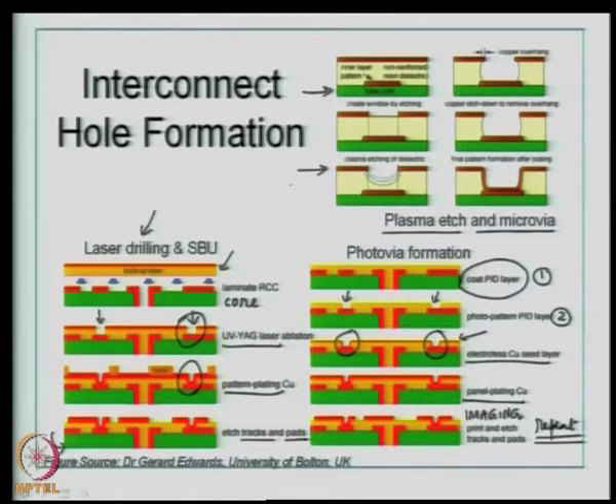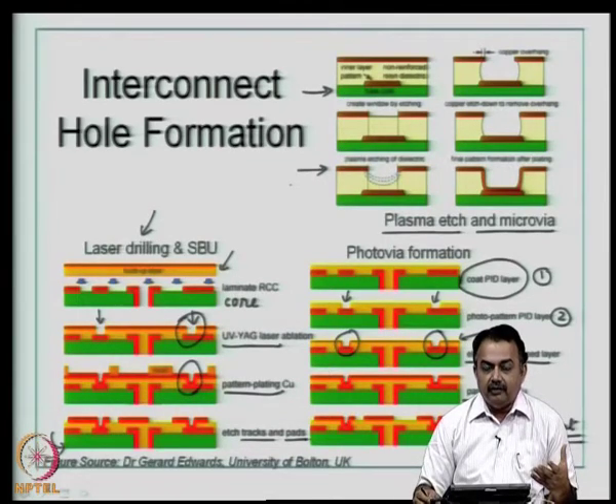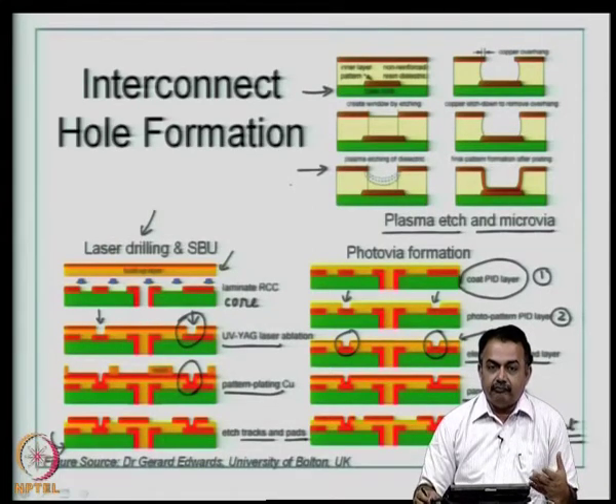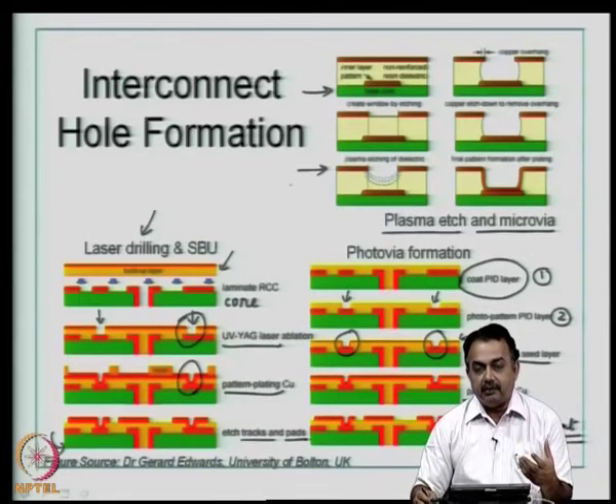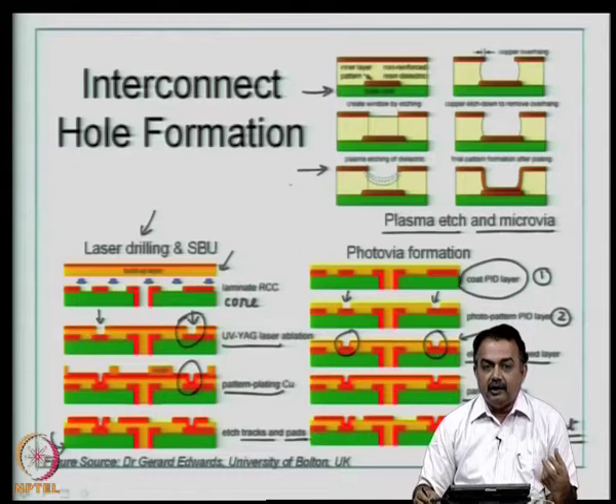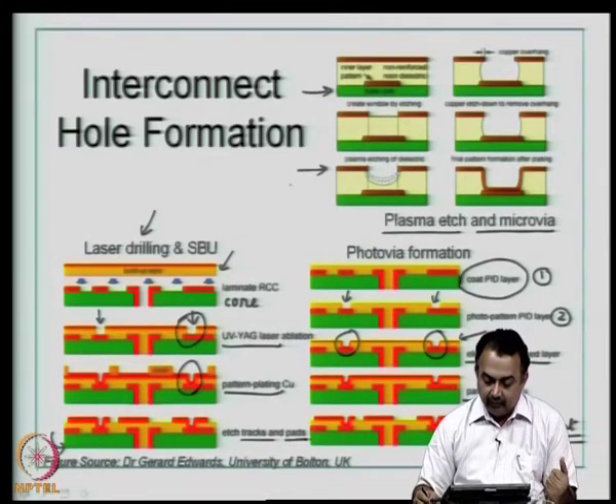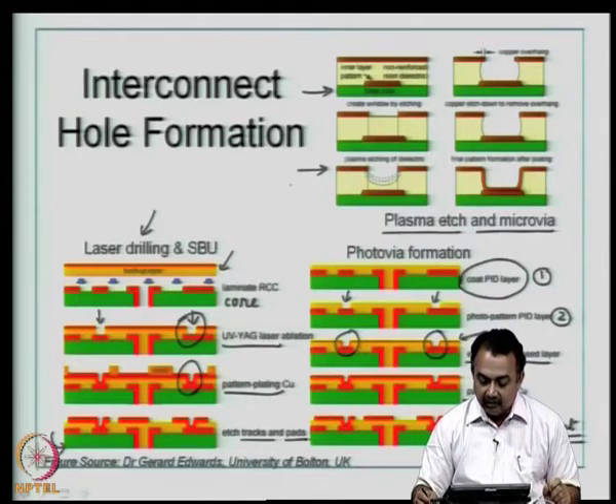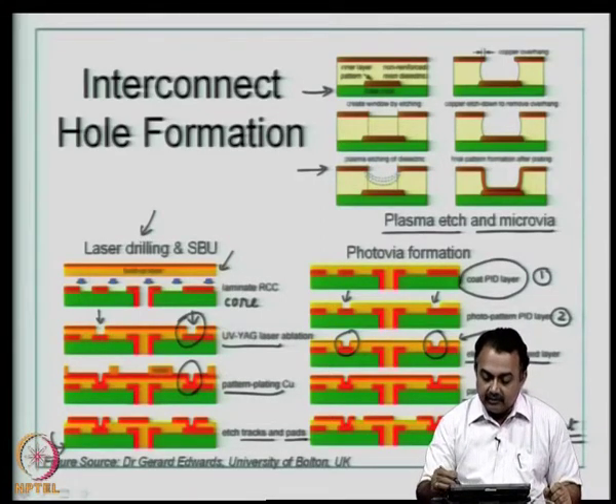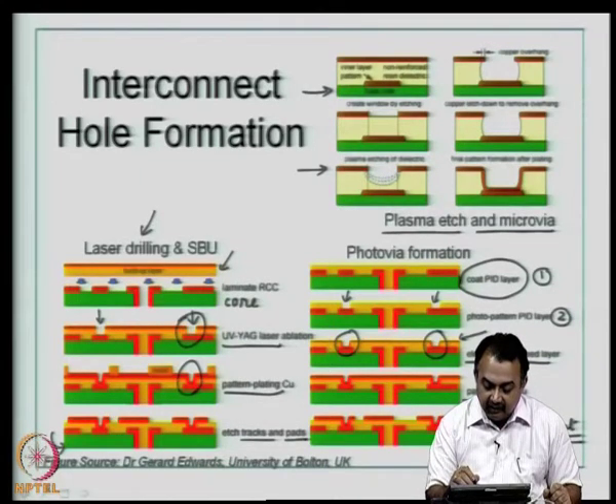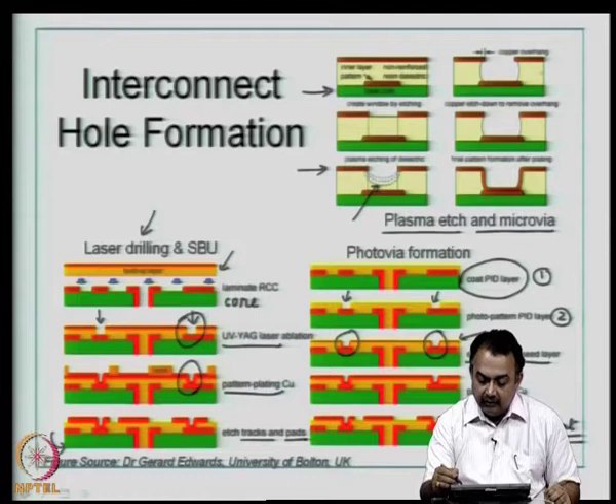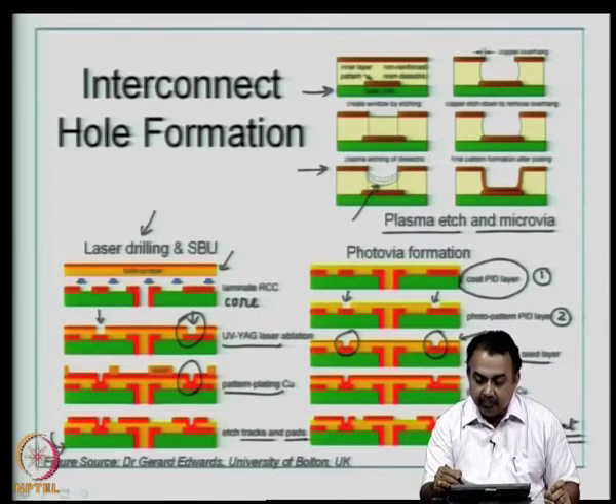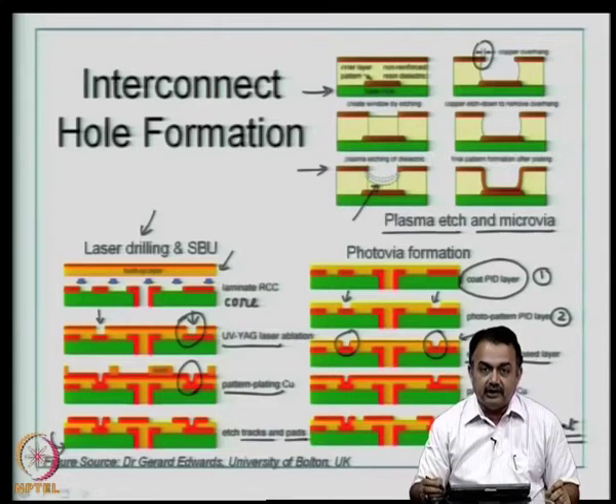So, basically the plasma is generated in a chamber where, for example, you have two gases, let us say CF4 and oxygen interacting together, and you get a plasma from the resultant free radicals or ions at higher frequencies. Now, these resulting ions or free radicals will react with the dielectric material, and basically it is a slow process, but you can see here the material is ablating, the dielectric material is removed here, you can see in this particular figure, and then the copper etching is done basically to remove the kind of protrusion that you can see here that the plasma etch has not taken care of.